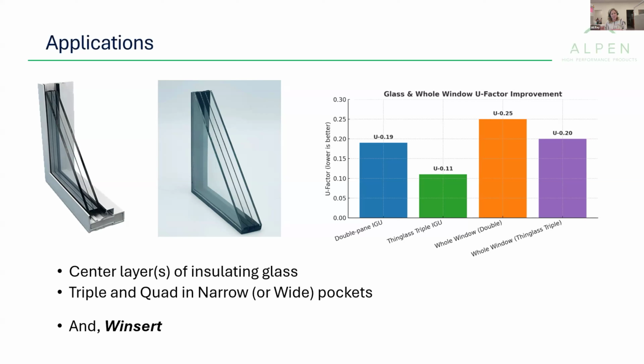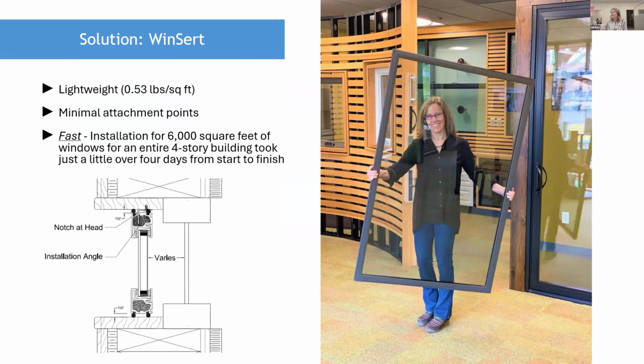But on top of just retrofitting narrow insulated glass pocket frames, we've also started innovating on retrofit solutions like Windsert. Windsert is a secondary window product that is very lightweight. It's using that thin glass, about 1/2 pound per square foot, in a very simple fiberglass frame. So this means that it's a lightweight, easy to deploy product that has very fast installation. So we did a project in Vancouver with 6,000 square feet of windows, and it only took us about 4 days, and most of that work was done at night. So we just had to ask folks to clean off their windowsills, and we could just slide the Windserts in, and they come back to a fully retrofitted window.